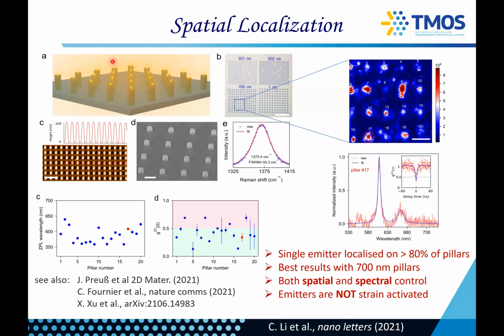The reason, or our hunch is why this works the best, is because it matches the enhancement of light properly. One micron is probably too big, so it becomes like a flat bulk surface. And 300 nanometers is a bit too small, so it creates a lot of strain fields, and the hBN is maybe a bit strained. So in this regard, 700 seems to work better. But it's a very empirical study.